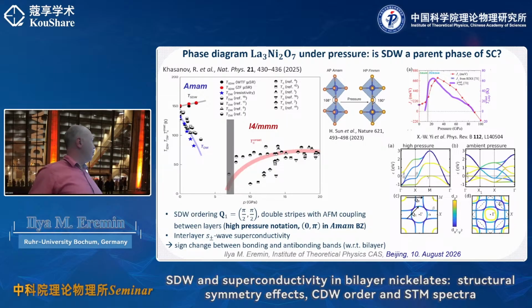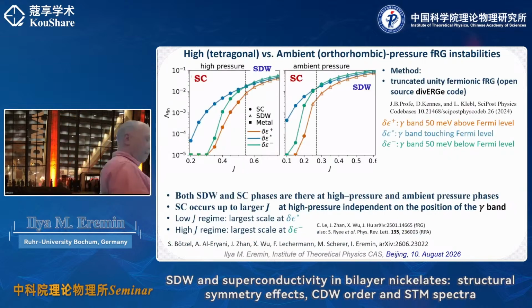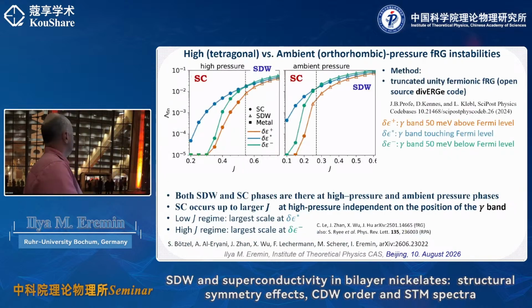And this is where the part of our collaboration with Shizhen Wu and Jun Zhang comes in. So essentially, we just said, okay, we know it's not superconducting, but we can still run an FRG code both at the ambient pressure and at the high pressure phases to see what's going on, what is the leading instability. And then you have a certain value of U, typically 4 electron volts or something like this. And then you start to vary the Hund coupling to see what is going on.